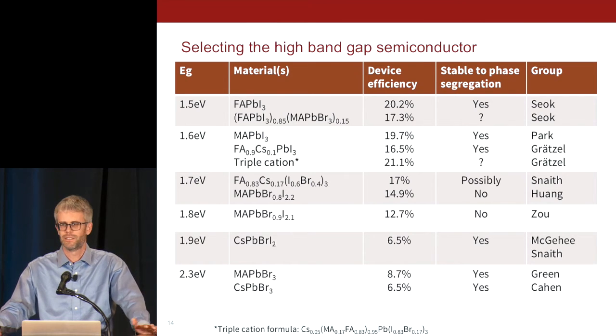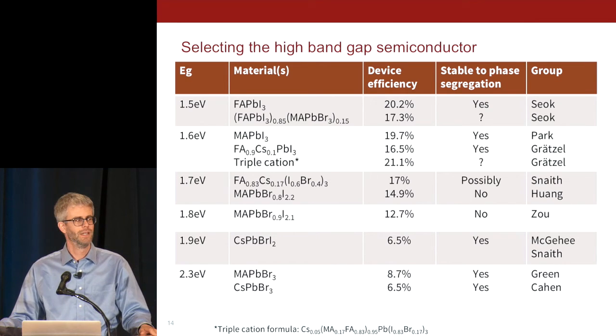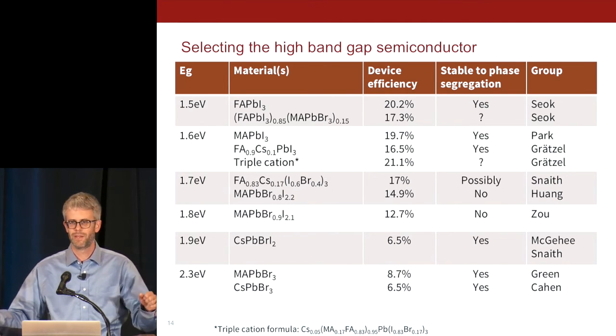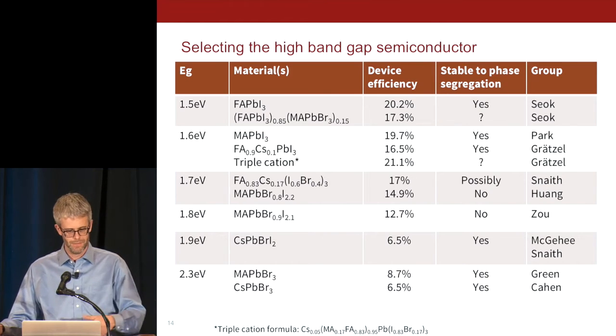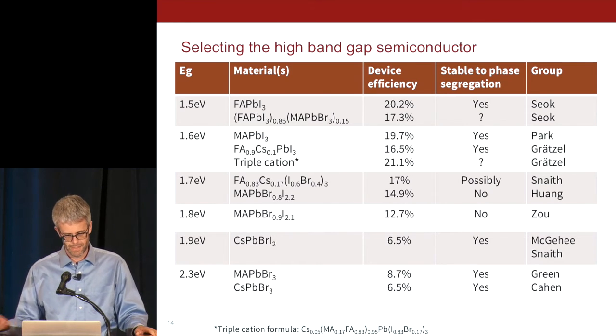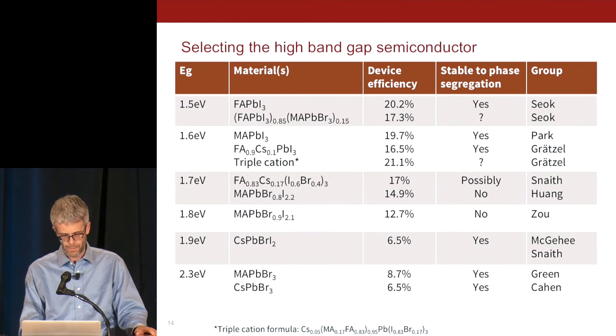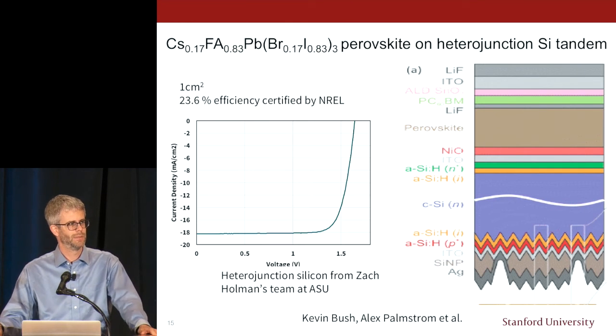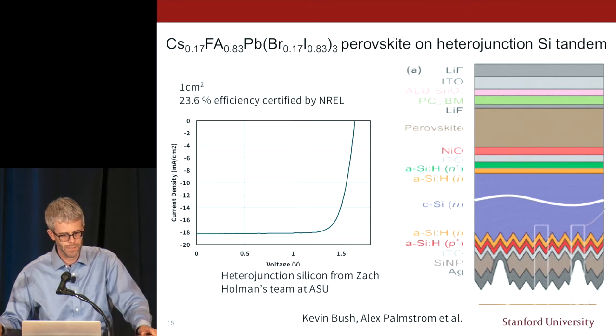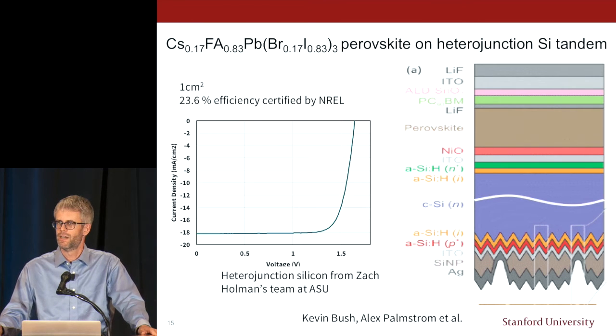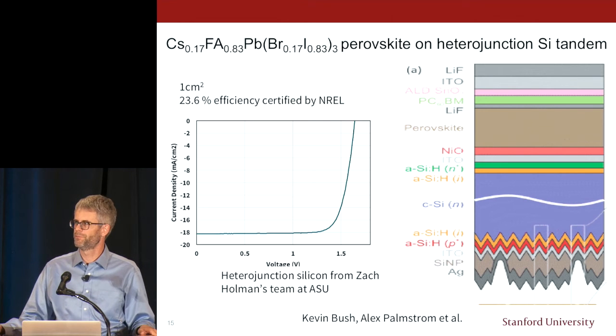I have to acknowledge there are literally a thousand or more researchers out there in the world who are hard at work in the labs as I speak, developing all these new compounds, and here we catalog some of them. We don't yet have our ideal band gap of 1.8 eV, but we do have the cesium, formamidinium, lead, bromide, iodide compound that works really well, has a band gap of 1.6. It's very stable.